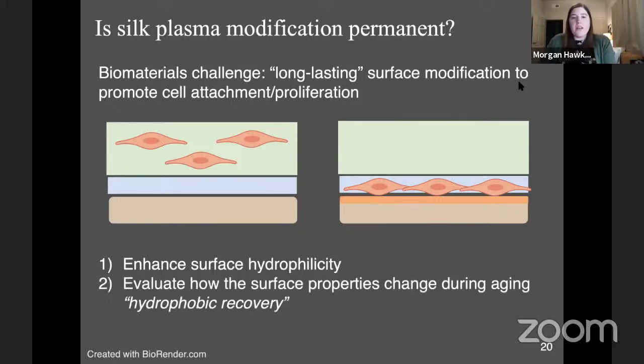So another one of our goals with this project was not only to make the surface hydrophilic, but observe how permanent that hydrophilic modification was. If we're treating a hydrophobic polymer surface to induce hydrophilicity, it's very common for the polymer to undergo a process called hydrophobic recovery. And what that means is that the polymer chains actually reorient after modification, which subsumes the hydrophilic functional groups. And this is somewhat thermodynamically complicated, but the end result is that the surface rearranges either back to its original state or more closely resembling its original state. So we wanted to study whether or not this process occurs in silk, because this could have implications on the shelf life of silk modified constructs.